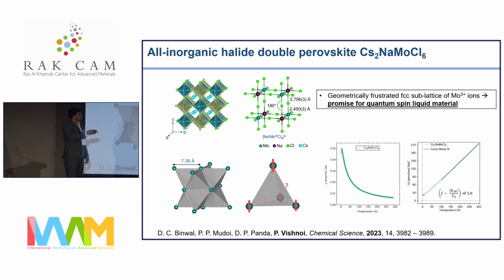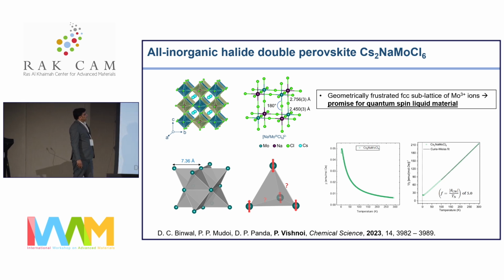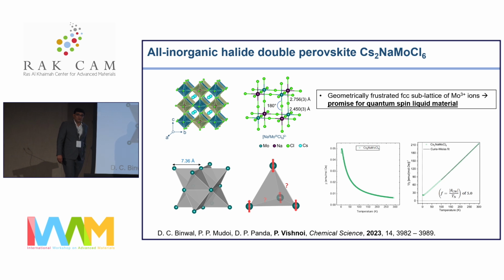We see, of course, there is a magnetic exchange interaction that happens around 3.5 Kelvin or so, but we see the Curie-Weiss temperature, which is quite high here, about 15 or so. So we see a frustration factor close to 5. That means there's some amount of frustration in this material, which probably indicates that such materials could be a promising quantum spin liquid moving forward.